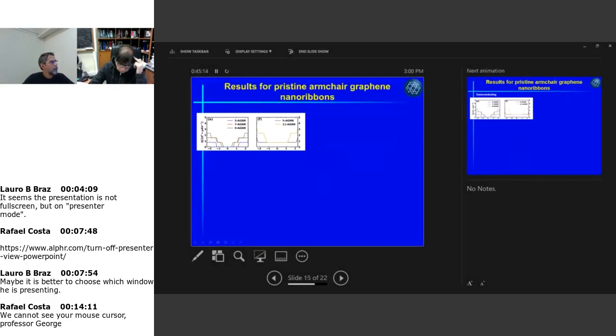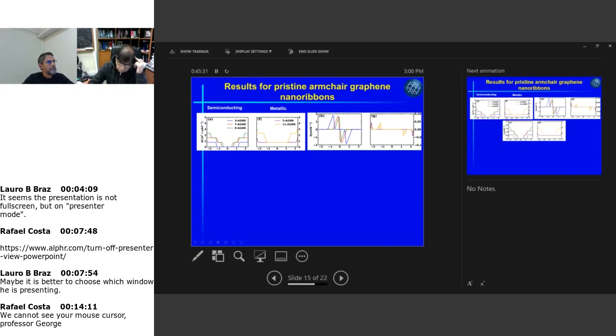So here we have the conductivity for five different armchair graphene nanoribbons. These three are semiconducting and these two are metallic. This is the Seebeck coefficient, left side for these three, right side for these two. And you can see immediately on the right side, in panel G, that the Seebeck coefficient is of the order of 0.1 or less, 0.05, much smaller than the Seebeck coefficient on the left. Why? Because, as I told you, metals are very bad thermoelectric materials. They have a very low Seebeck coefficient, so their ZT is very small.